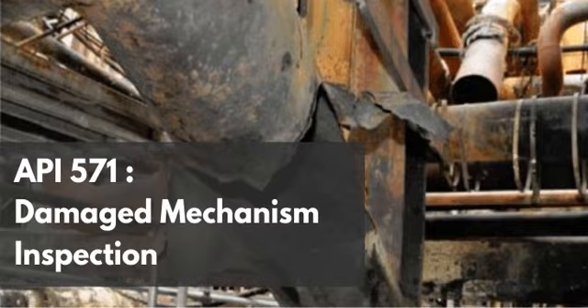Why MEA specifically? I mean, why does that one fail so dramatically? MEA is a primary amine. It is highly reactive, which makes it fantastic at absorbing acid gases quickly and efficiently. Right, it's a great sponge. But that same chemical reactivity means it is much more prone to thermal degradation at lower temperatures compared to a tertiary amine like MDEA. So while you must monitor all your amine systems, MEA systems with high CO2 loading have a brightly painted target on them for this specific degradation mechanism.